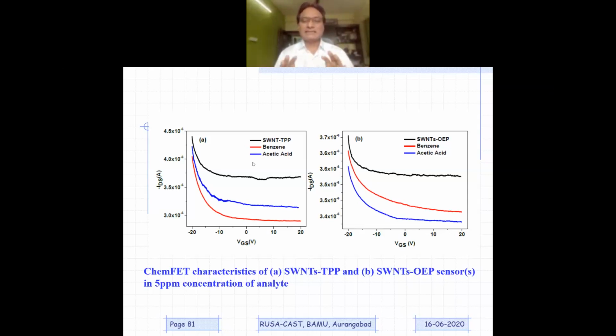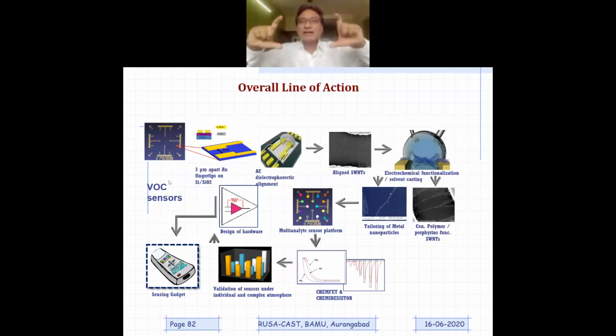Once we confirm that you have got all 16 devices and you have bridged those 16 devices with CNT, the next step is to modify these CNTs with 2 different materials, as I mentioned earlier: organic conducting polymer and porphyrin. Modification of CNTs in a 3 micron gap is a challenge. The gap is only 3 micron wide, and the total device height is going to be 250 micron. Therefore, coating CNT is going to be one of the challenging aspects.